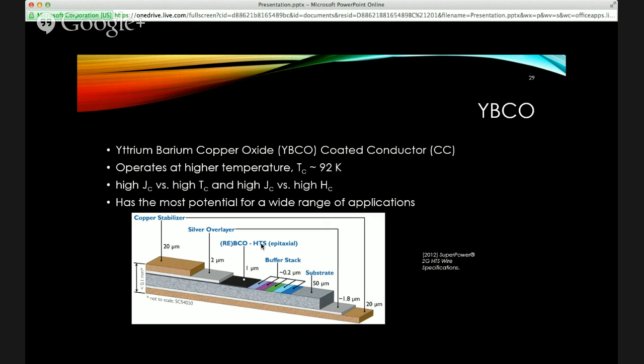I actually looked at YBCO, which was one of the high temperature superconductors that I mentioned earlier. And this is because it has a higher temperature, so the critical temperature for it is 92K. And it has a high JC for the high TC and also a high magnetic field. Meaning that, think of that superconducting dome that I showed you before, it's larger.